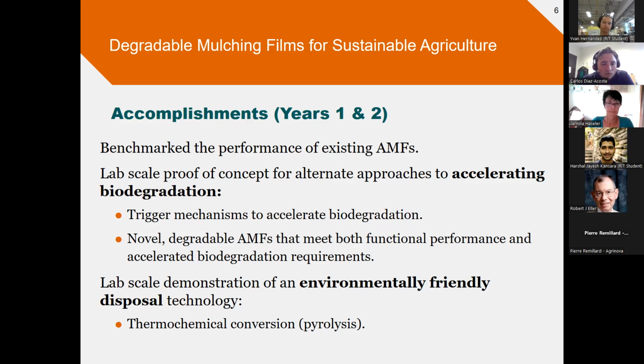At the same time, we started developing this new idea, what we call a genuine breakthrough in the novel structure for biodegradable films, and have them meet both the functional performance and the accelerated degradation requirements. We did a lab scale demonstration of the environmentally friendly disposal technology, the thermochemical conversion using pyrolysis. So basically we commingle organic waste with conventional mulch film, and we demonstrated that this is a viable idea. A paper was published on this concept with a techno-economic analysis. And for those of you, I'm going to ask Ivan to put the website in the chat. And if you visit the website, you can learn more about pyrolysis and the commingle with mulch films.